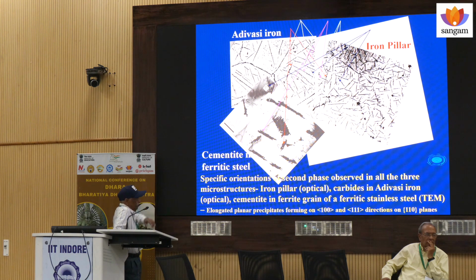And here you see a modern ferritic stainless steel, where from the electron microscopy you can identify the possible orientations of the cementite. And if you align the grains in a particular orientation, there would be a one-to-one correlation with the cementite, which is identified through electron microscope of the modern steel in the ferrite matrix, and the orientations would exactly match. So from the orientation relations, this is the indirect evidence I was talking about. So it is cementite and not related to the phosphorus. But phosphorus is more uniformly distributed, we believe, in the matrix, and that is giving the corrosion resistance.